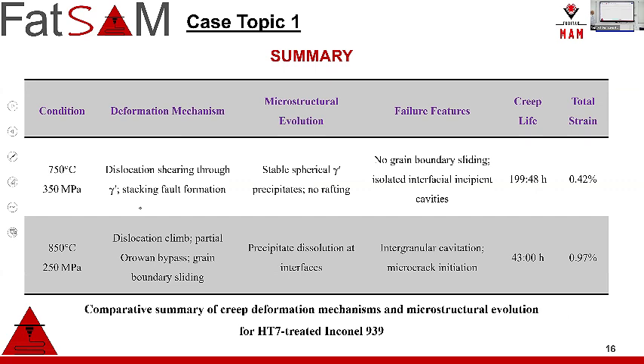Summary: at 750, we saw dislocation shearing through gamma prime, which is stacking fault formation, or in some cases, some superalloy people say anti-phase boundary formation, because it is not like steel. These stacking faults or twinnings can cut through the precipitates compared to steels, where they were in general partial dislocations between two intergranular grains, which are austenitic phases. But here it is a little bit different.